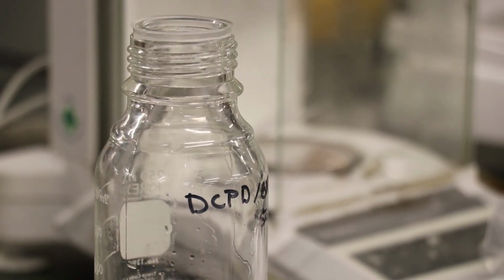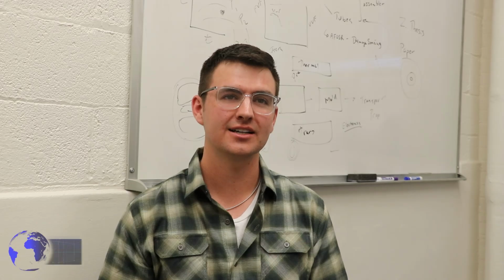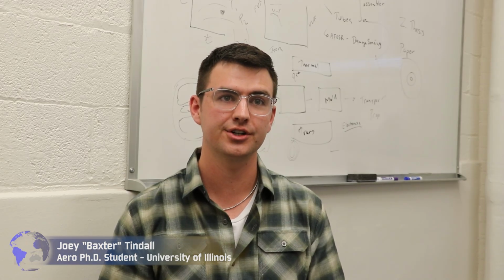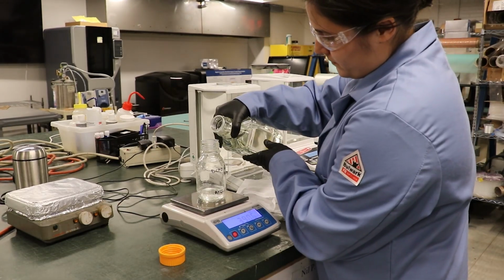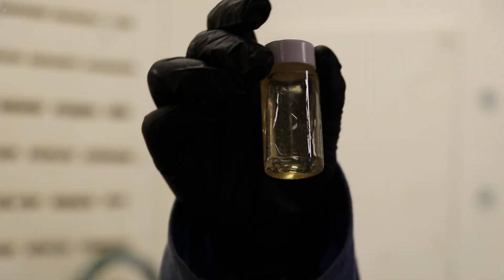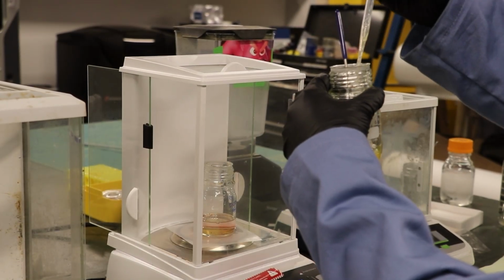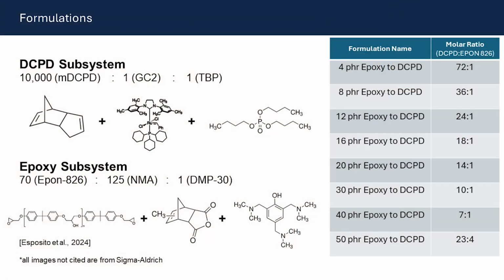The main properties we're looking for in our resin are low energy and a fast and efficient cure. This will be done by using frontal polymerization. DCPD has low viscosity, easy composite processing, low energy curing, good toughness, but poor interfacial carbon fiber properties. Epoxy, on the other hand, is a much more viscous and stickier resin that adheres well to carbon fibers, and it has been studied very well at both the Air Force and just in space in general. We have hypothesized that DCPD and epoxy co-cured mixtures will have a good balance of processability, such as low viscosity, low energy curing, and improved composite mechanical properties in comparison to either DCPD or epoxy alone.